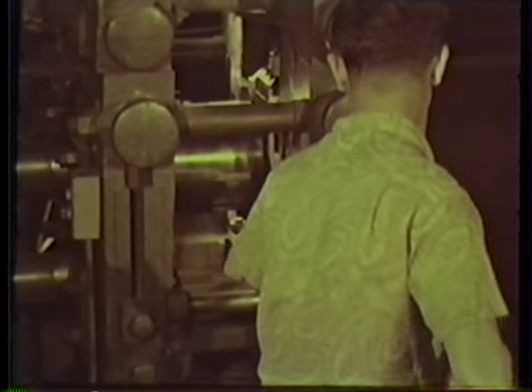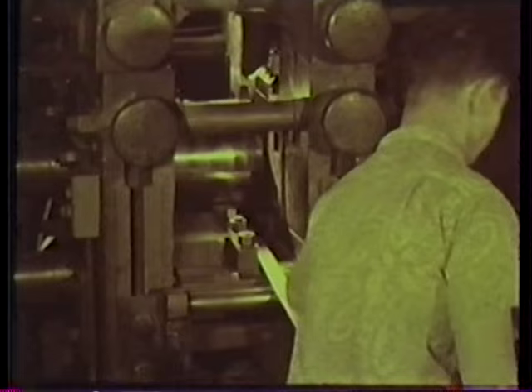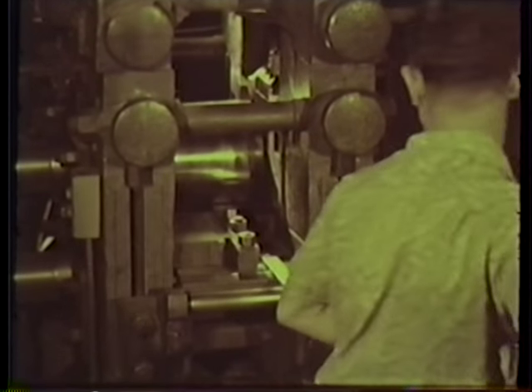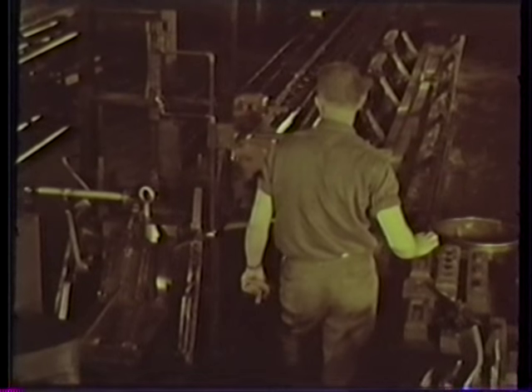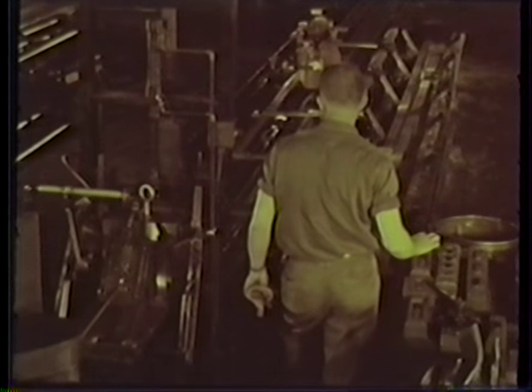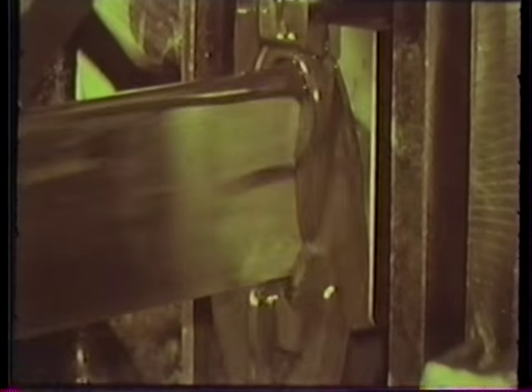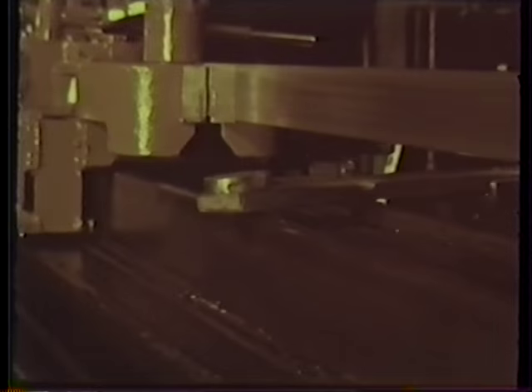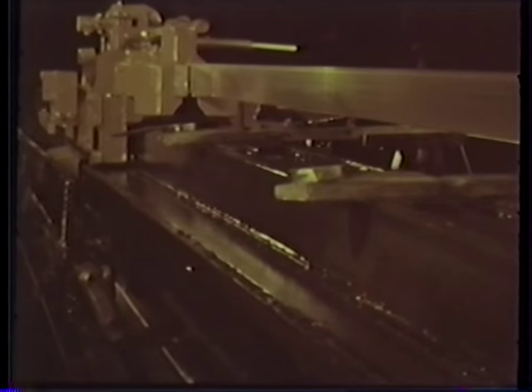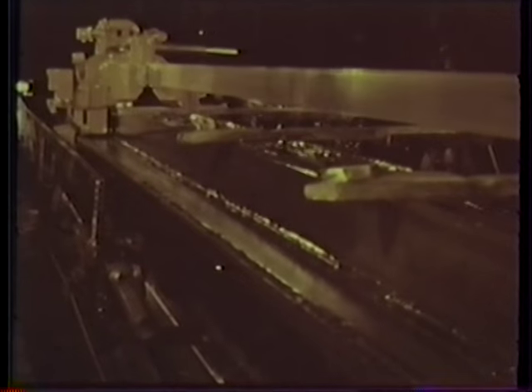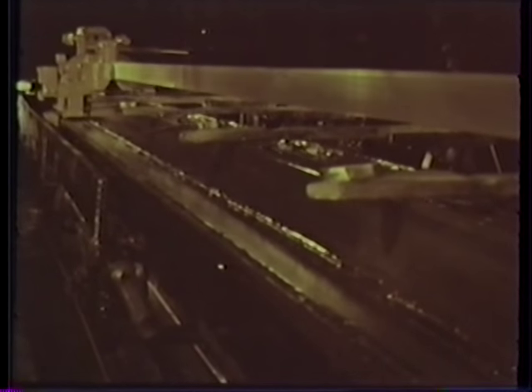A cold rolling follows, which gives the copper a preliminary sizing necessary for the bench drawing which is to follow. Probably the most crucial step in the entire preparation of commutator copper is bench drawing. Not only does this operation determine the final dimensions and the surface finish, but also the cold working of the metal greatly alters its hardness, grain size, and tensile strength. As a result, up to 4 final draws with intermediate annealing may be necessary to obtain the exact properties called for in the specifications.